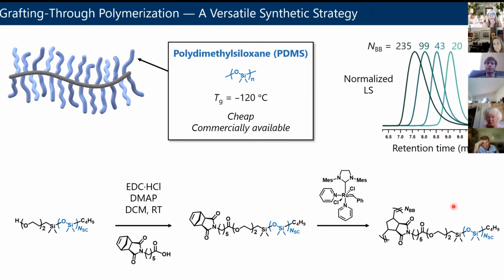So you're monitoring the eluent as it comes out of the column, that's the x-axis, as a function of time. And your detector, in this case a light scattering detector, gives you signal when it starts seeing high molecular weight polymers come out. And so you can see that the signal depends on how long you wait in the experiment, and it also depends on how long a backbone we synthesize, where longer backbones come out first in this characterization method. And you can see here we can systematically control the backbone length.